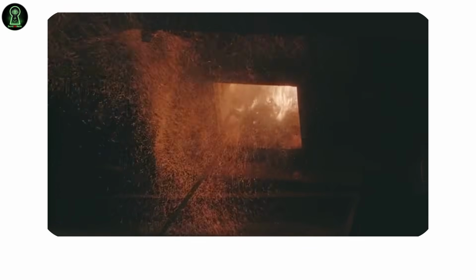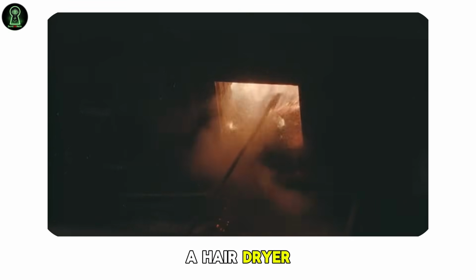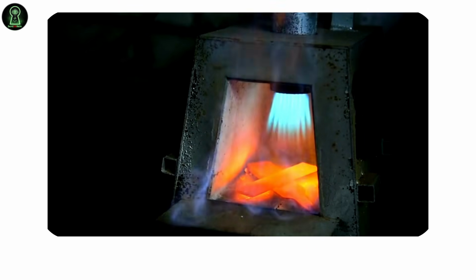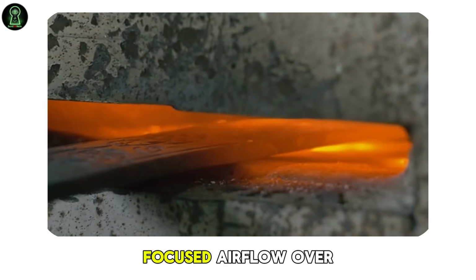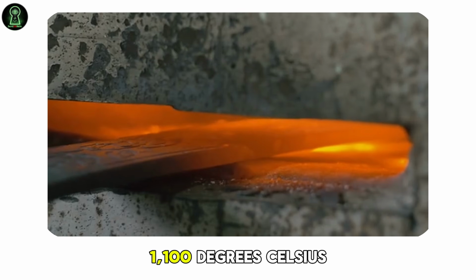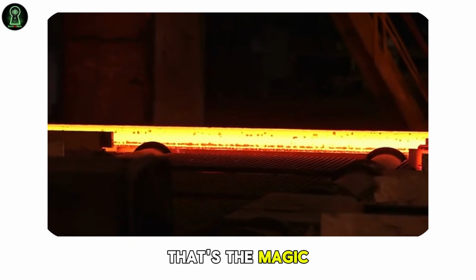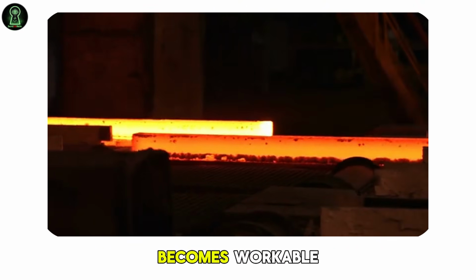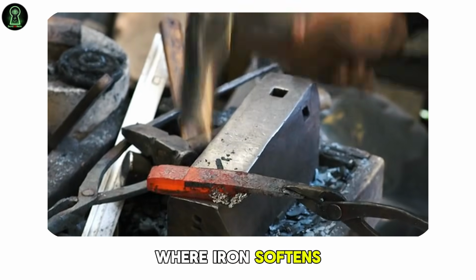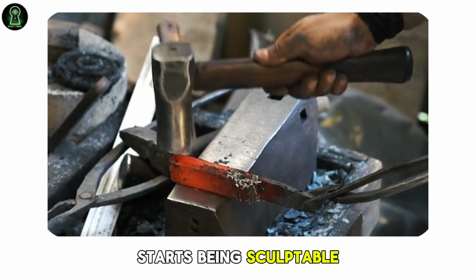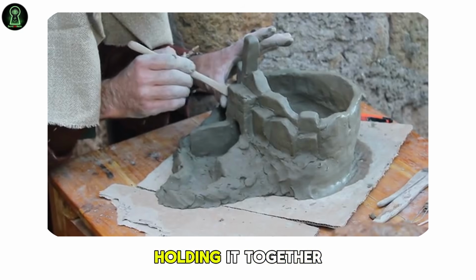It climbs. Add a simple air source, even a hairdryer, and the temperature inside that chamber starts pushing past 700 degrees Celsius. Add better airflow, 900 degrees. Sustained, focused airflow, over 1,100 degrees Celsius. That's the magic number. That's the point where steel becomes workable, where iron softens, where metal stops being rigid and starts being sculptable. And the clay, it's not just holding it together.